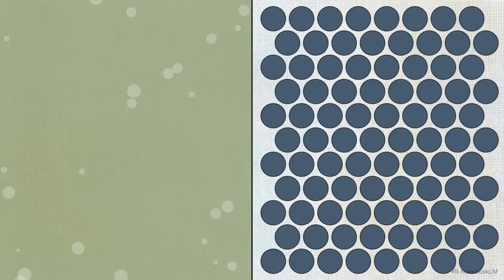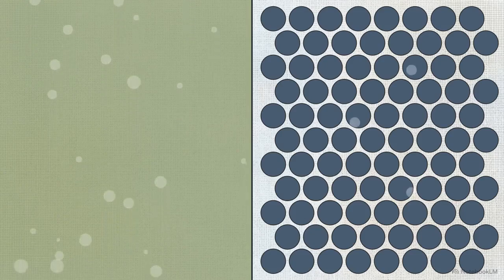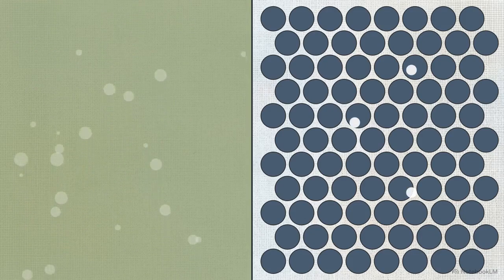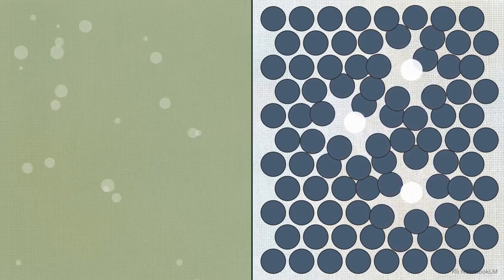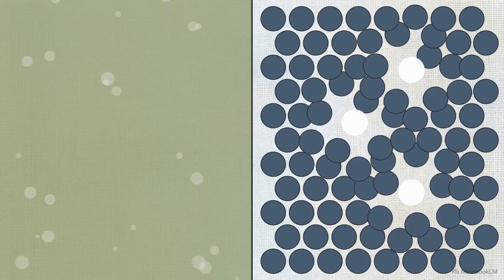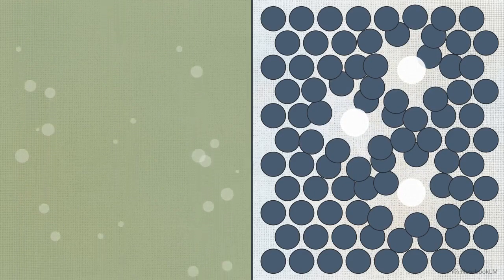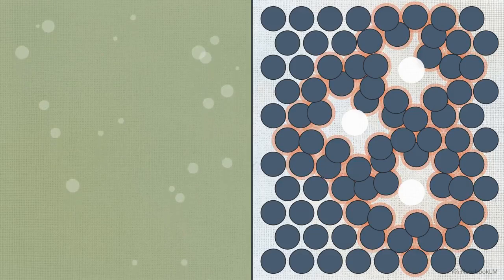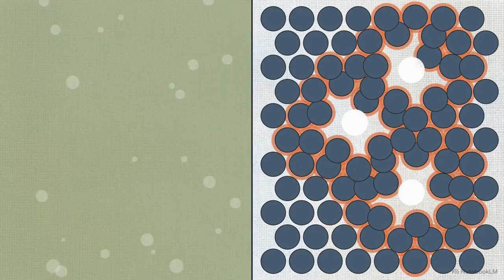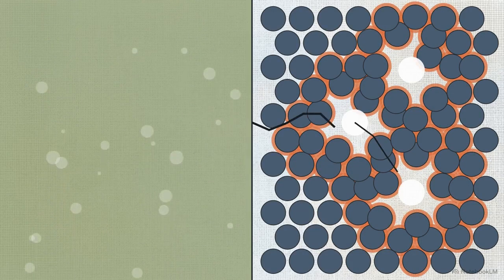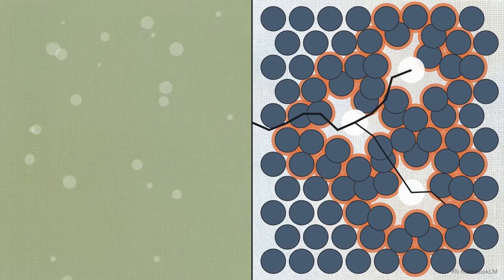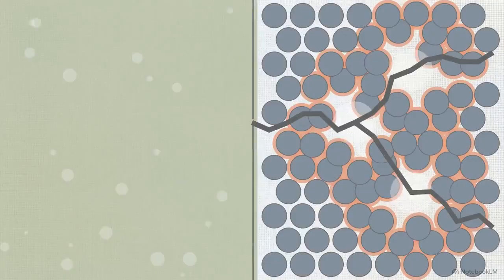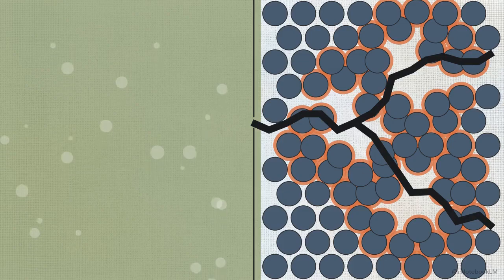The small hydrogen atom forces its way directly into the metallic lattice of the steel wall. Once trapped deep inside the metal, those isolated hydrogen atoms recombine into larger molecular hydrogen gas. They expand, generating immense localized pressure that physically pushes the steel grains apart. Microfissures erupt inside the wall. They rapidly link together, ripping a jagged path outward until the pipe ruptures. This is sulfide stress cracking.